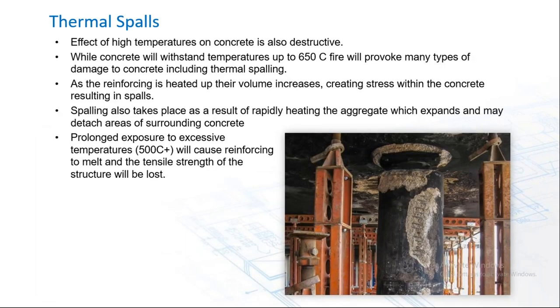The effects of high temperature on concrete can also be destructive, not necessarily to the concrete itself, although the expansion of some aggregates can also create these thermal spalls. But more frequently, it is actually the expansion of the reinforcing steel that creates the internal pressures to overcome the tensile strength of the concrete as well. And with prolonged temperatures above 500 degrees C, we'll see the reinforcing melt and the tensile strength of the entire structure is lost at that point.